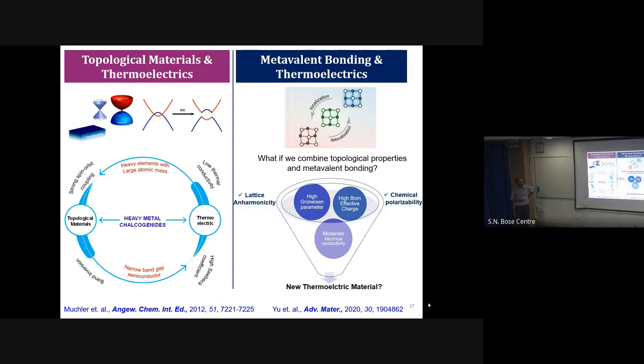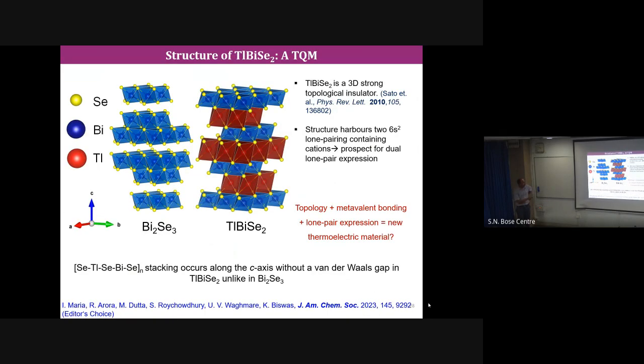So let's see what happens. This is a known compound, thallium bismuth selenide, TlBiSe2, and it is predicted and shown by ARPES to be a 3D strong topological insulator. And we all know the structure of bismuth selenide. It has a quintuple layer and van der Waals gap. Again, quintuple layers are there, 5 layers. But in thallium bismuth selenide, these gaps are closed.